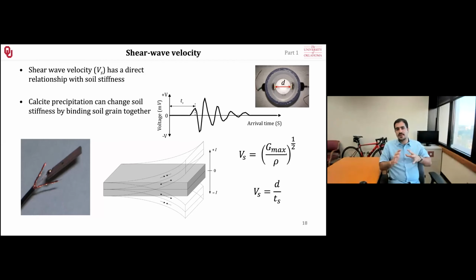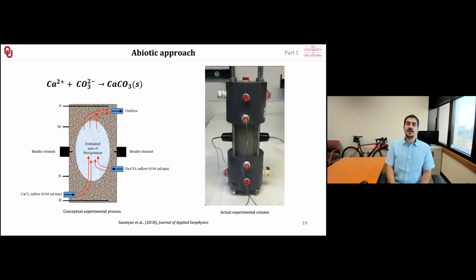Now, this would be sort of a ground truthing engineering method for my geoelectrical measurements in the field, in addition to direct sampling. But before using the microbial approach, I have to see if my geoelectrical measurements are actually sensitive to the cementation agent, the calcite, right? Do I even get any signal if I have calcite? If I don't see any geoelectrical signal if I have calcite in the soil, then what's the point?